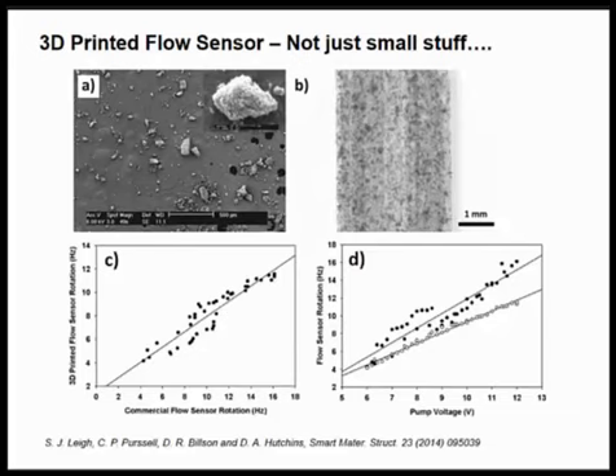A graph here showing the correlation between our printed flow sensor and the commercial flow sensor, so we get fairly good agreement. The graph on the right shows an enclosed, completely closed loop water-based system with varying pump voltage to increase the flow. A nice linear one at the bottom is actually our printed one, it's not the commercial one. So it's actually in this case behaving better than the commercial sensor for this application.